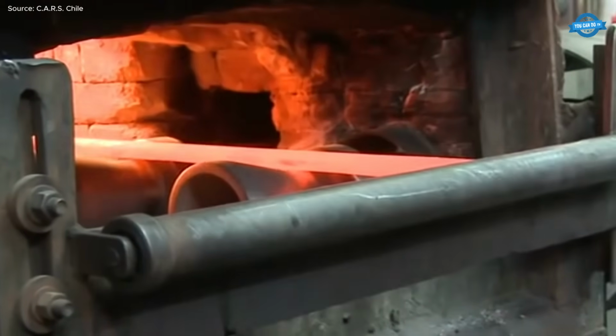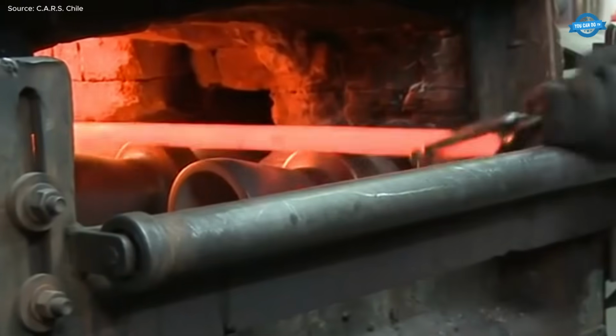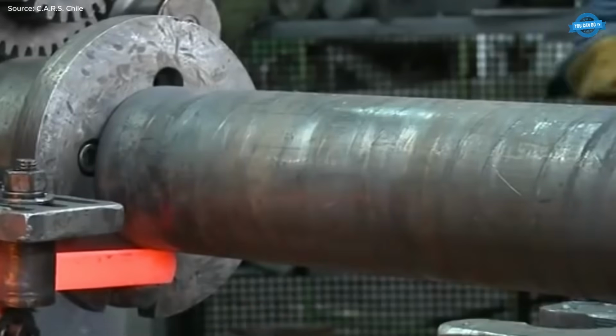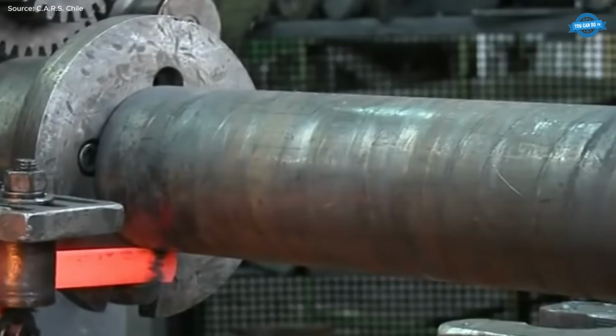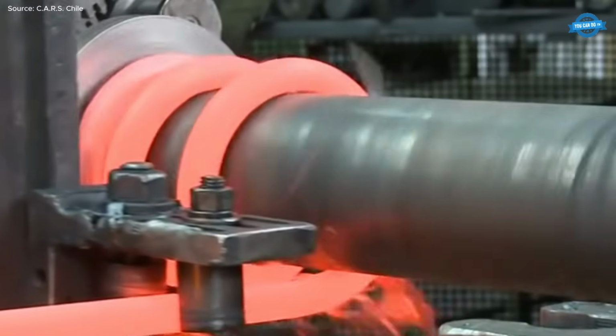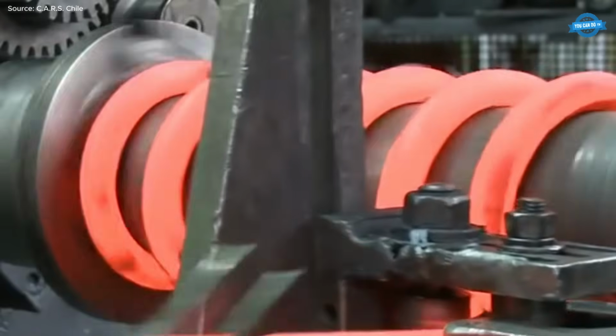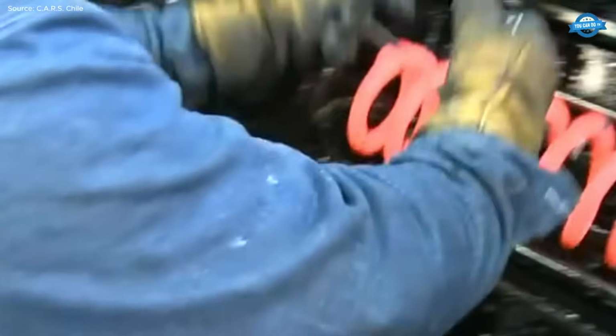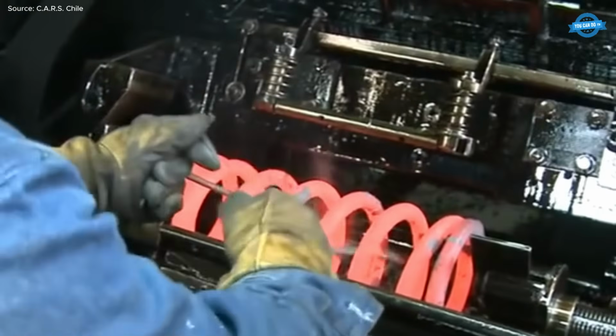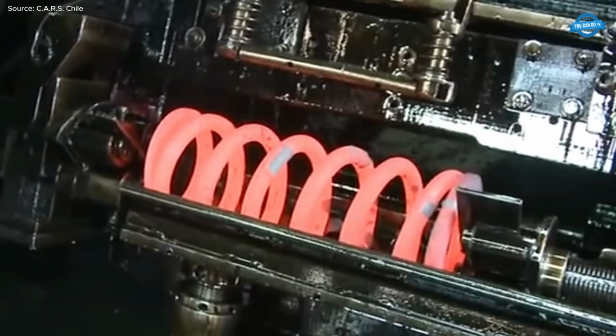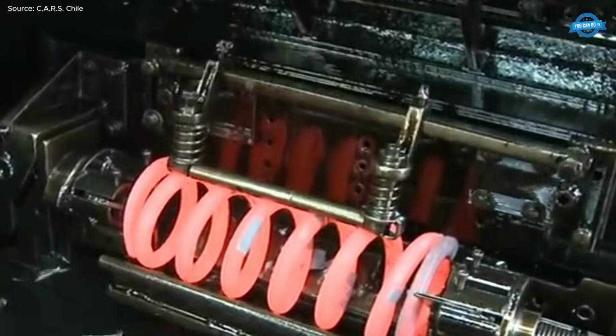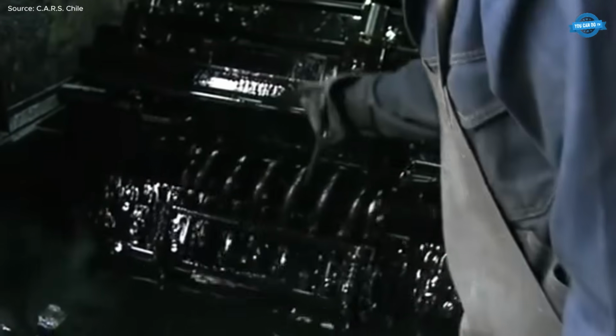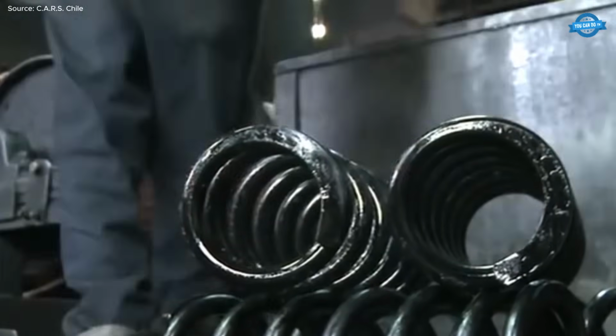Next comes controlled heating to achieve austenitization, followed by coiling in precision dies that ensure consistent geometry. While still red hot, the spring undergoes oil quenching to transform the microstructure into martensite, producing maximum hardness. Because the quenched material is extremely brittle, tempering is performed at roughly 390 to 460 degrees C for at least 1 hour in a controlled atmosphere furnace to restore toughness and relieve internal stresses.